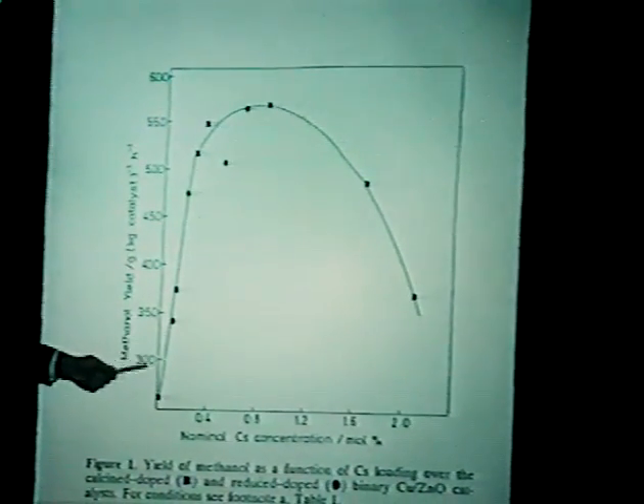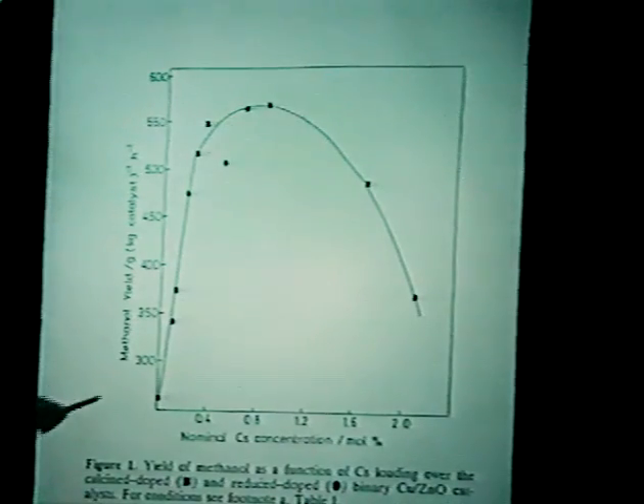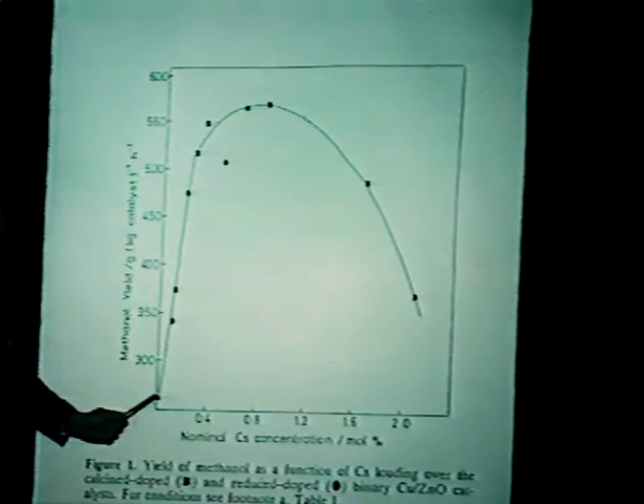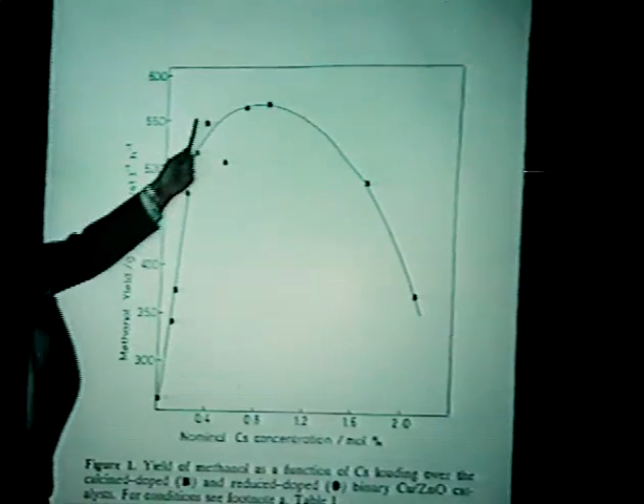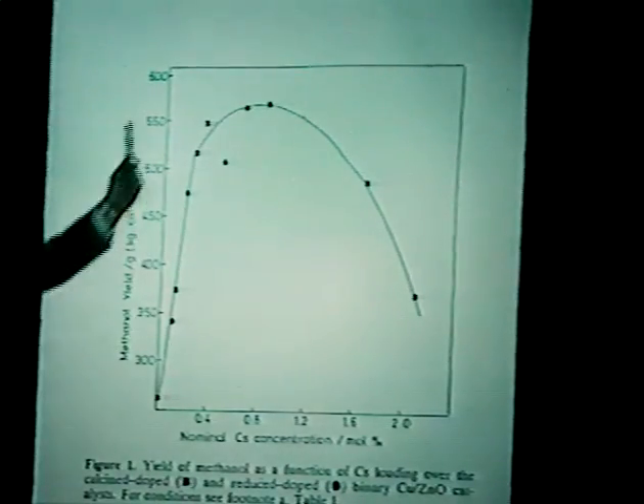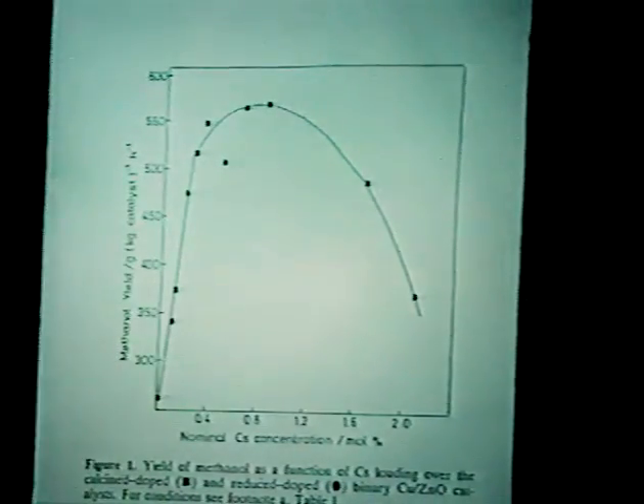Compared to the cesium undoped catalyst, this is a 300, so there's a scale below here, the effects of small concentrations of cesium are large, and then when the concentration of cesium is larger still, the activity goes down because we have a competition with this bifunctionality between the basic sites and the hydrogenating sites. By the time we are putting too much base in, we're killing the hydrogenation sites that is here.